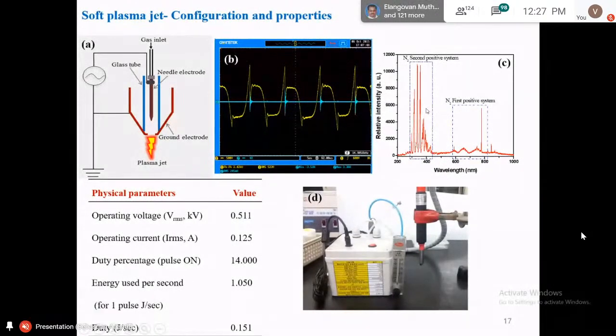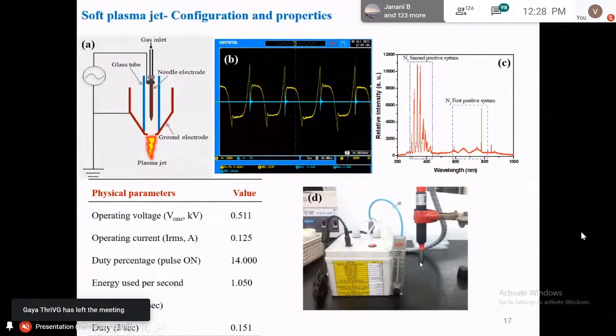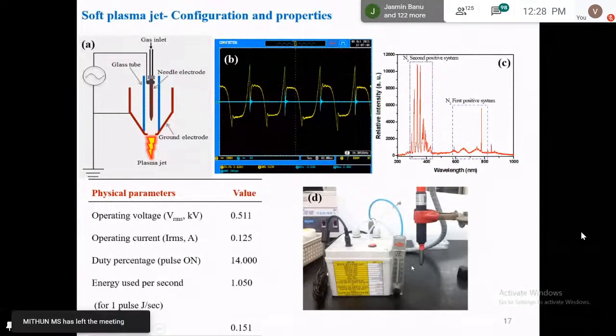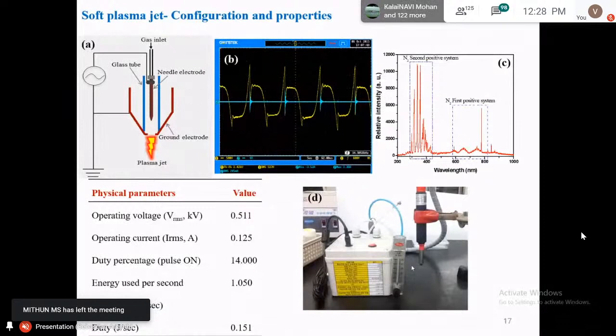VI curve, and then we have to use some gases to ionize. That will give plasma. So we can use various gases ranging from air or argon or nitrogen, any kind of gases. It depends on the gases we use. The plasma consists of different plasma species. If we use air as a gas, we get nitrogen ions and electrons as the plasma species. If we use argon, that argon is ionized and we get argon ions and electrons as the plasma species. So those species come out here, and we expose this plasma to our nanomaterial solution. That interaction of plasma species with nanomaterial solution gives rise to different sizes and shapes of nanomaterials. So this is the phenomenon we see in plasma-assisted synthesis.